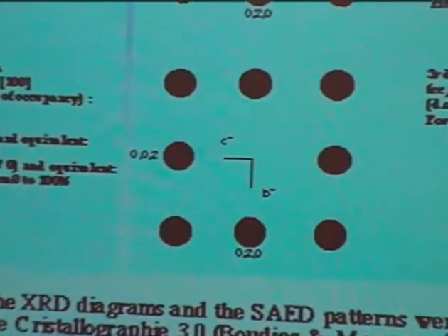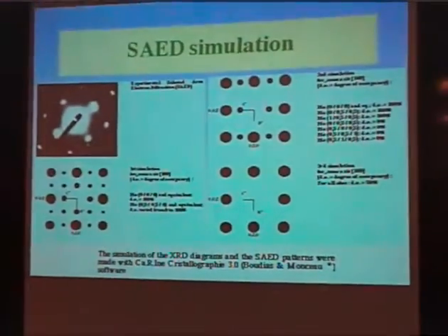You can also simulate the selective area electron diffraction made in transmission electron microscopy, and you can see that by taking out molybdenum from the sites where they should be, in other words, making vacancies of molybdenum in the structure, we finished with a very good fit of this SAED spectrum we get, which means that finally the product has a deficiency in molybdenum.